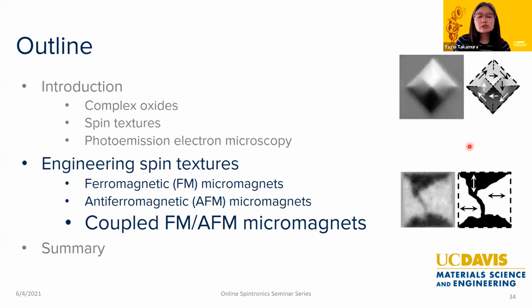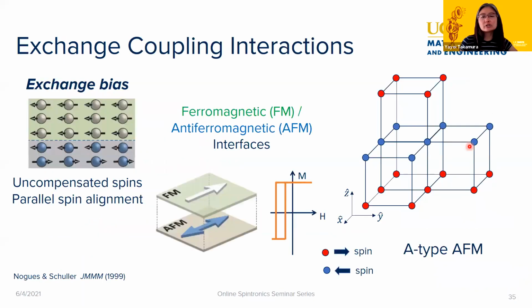Okay, so what I want to do is show quickly some examples where we can actually have coupled ferromagnetic and antiferromagnetic structures. In a case where you have a ferromagnetic antiferromagnetic interface, the typical exchange coupling interaction that we see is exchange bias. With strong exchange bias, you can get a horizontal shifting of your hysteresis loop away from center. This kind of exchange interaction usually occurs in what we might refer to as an A-type antiferromagnetic material, where you have all spins in one direction in one layer, followed by all spins in the opposite direction. That's how you can get this biasing of the ferromagnetic layer by the antiferromagnetic layer.